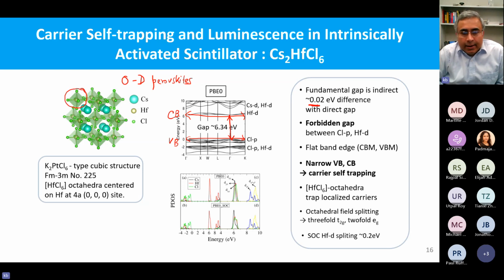Now, if you look at the density of states right there, just a little bit more detail. Again, you can see the nature of the states near the band edges, near the top of the valence band and near the bottom of the conduction band. We are always very interested in those. At the top of the valence band, you will see chlorine states right there. These are the same density of states from two different types of calculation, one including spin orbit coupling, the other without. You have hafnium there, a heavy metal, so spin orbit coupling is maybe important, and it's important to include it. So that's why we did both types of calculation.